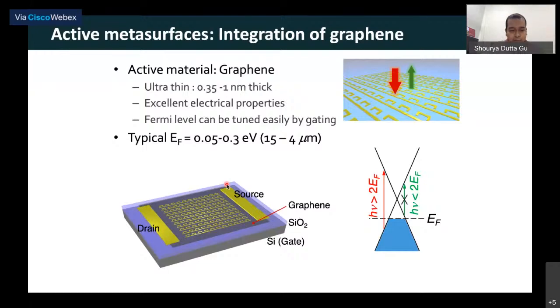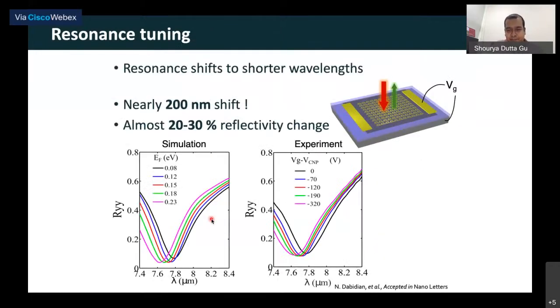So remember, a single layer of graphene, not multiple layers, placed on a layer of SiO2 and a silicon substrate. Now, if you connect two electrodes, placed on the graphene and the silicon, you can apply a field. By controlling this field, you control the Fermi level of graphene and thereby control its absorption. Now, we send light at normal incidence and look at the reflected light as a function of the gate voltage, the voltage that we apply between the drain electrode and the back gate, which is the silicon.